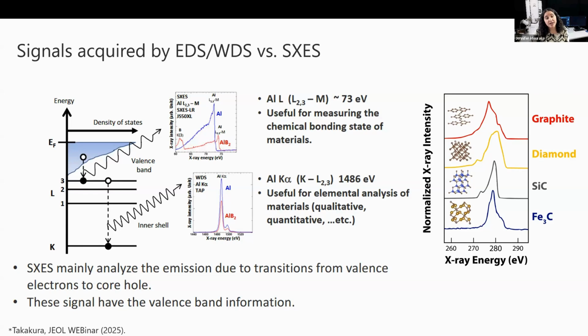The ultra-low energy X-ray lines detected on the SXES are more likely to contain chemical state information, even for the higher atomic elements. While the K transitions are generally not from the valence bands, these ultra-low energy transitions from the M or L shells do frequently involve transitions from the valence electrons, shown here. So thus, these signals can have valence band information, allowing one to determine the chemical bonding state of materials based on the peak's position and its shape.